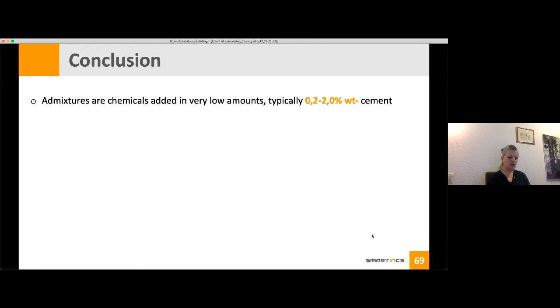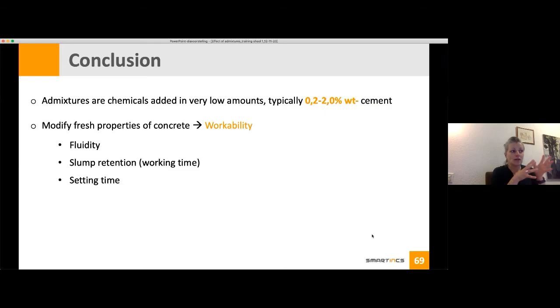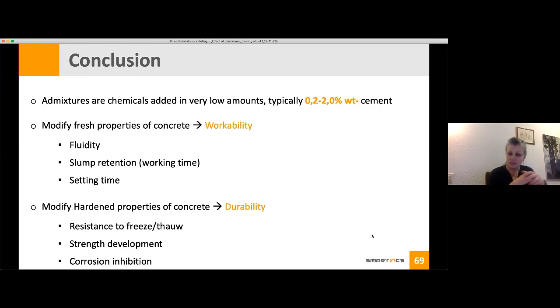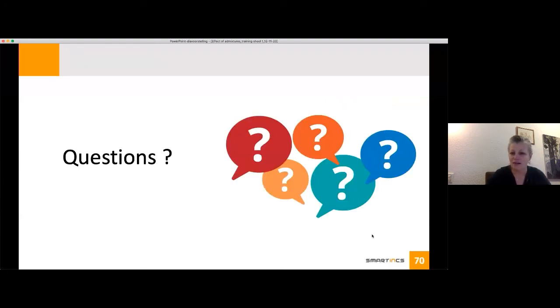So that was more a theoretical part of the presentation. To conclude, the message is that chemical admixtures are added to the concrete in very low amounts, but they can have a very big effect on your concrete properties. On the one hand, they can modify your fresh properties: workability, fluidity, slump retention, and also your setting time. They can also modify the properties in the hardened state of your concrete. So for durability performance, you can increase the resistance to freeze-thaw, have a better strength development, and corrosion inhibition. And of course, if you use less clinker inside your concrete mix, you reduce the carbon footprint. Are there questions for this part?